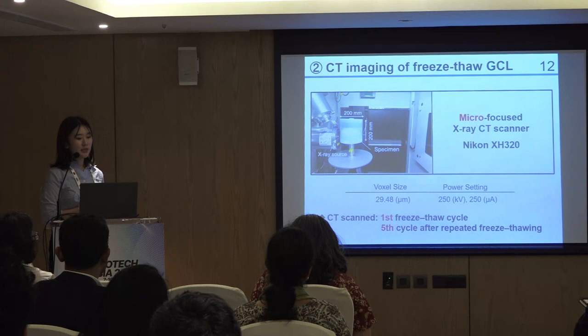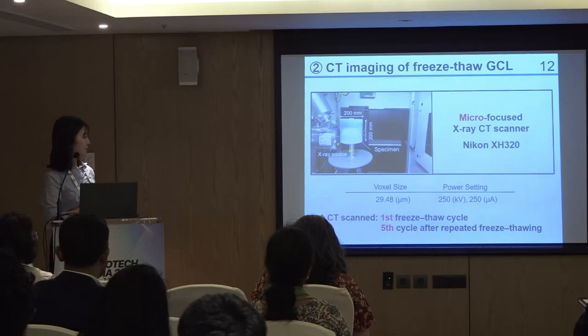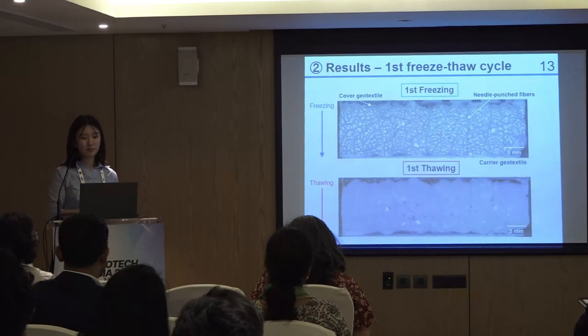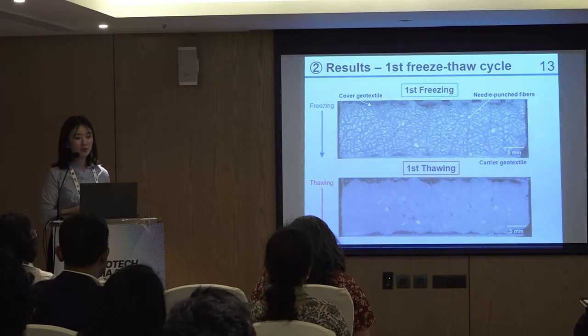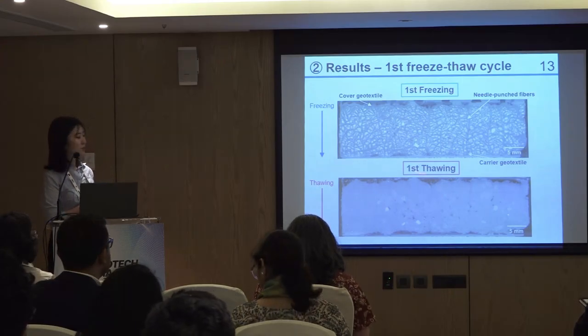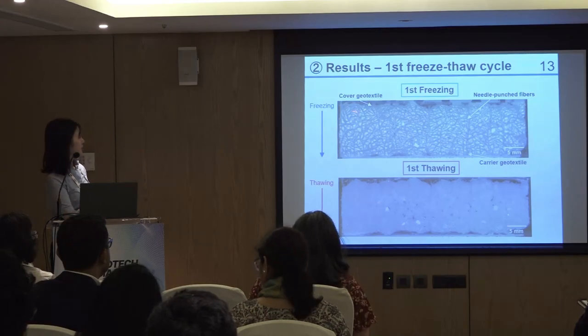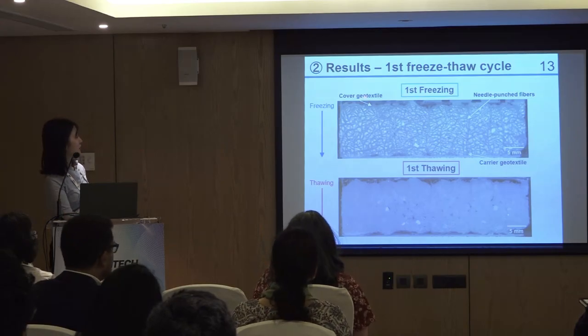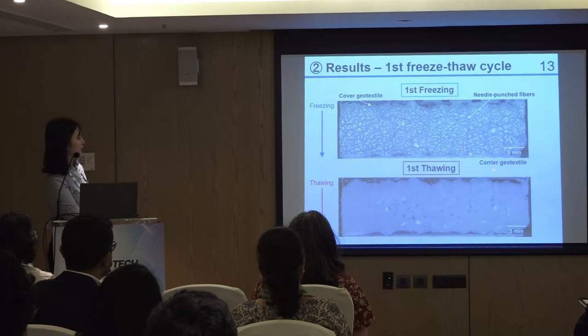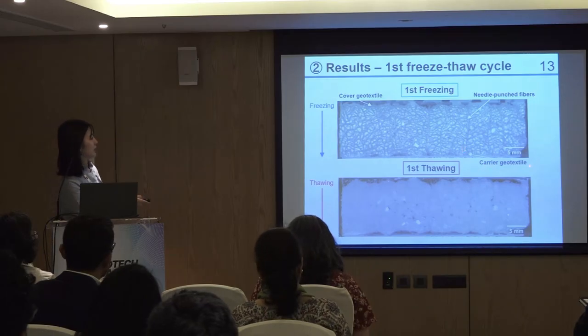This is a scene of scanning GCL. We scanned the GCL after the first freeze and thaw cycle and the fifth repeated cycle. These are the result images of GCL after the first freezing and first thawing. This part is the non-woven cover geotextile, and here is the woven carrier geotextile, and these are the needle punch fibers.